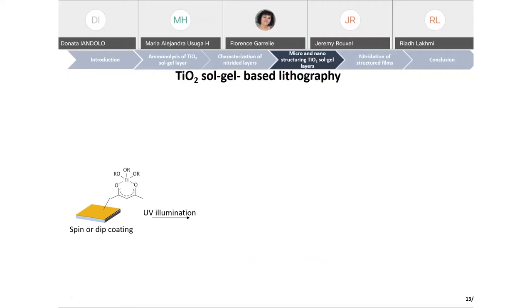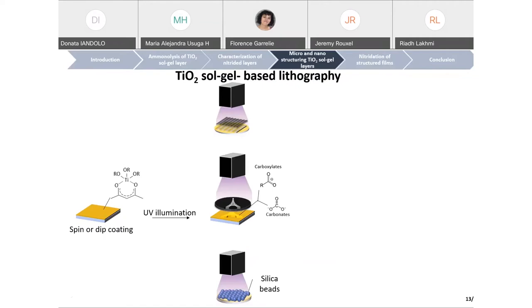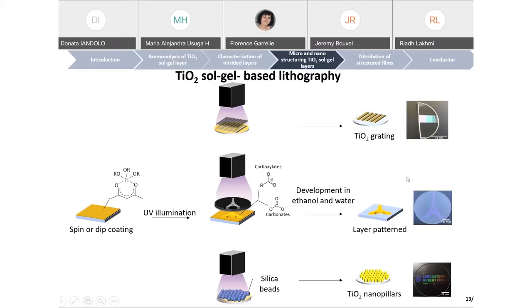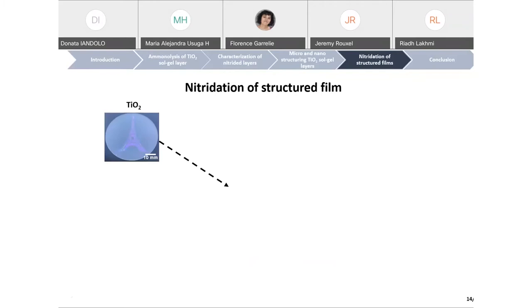there is a transformation of this complex, titanium isopropoxide benzoyl acetone, into a species which is insoluble in ethanol. We realized different methods of lithography, and when we develop in ethanol, the non-insolated zones are removed. Using this gel and the different lithography methods, we can fabricate microstructures such as logos and gratings, and nanostructures such as nanopillars. For the nitridation of the micro nanostructure films, this nitridation was realized using the RTA ammonolysis described previously, using the RTA nitridation.